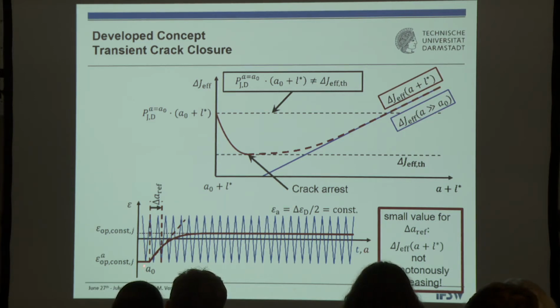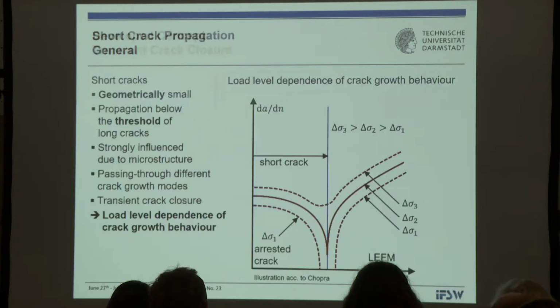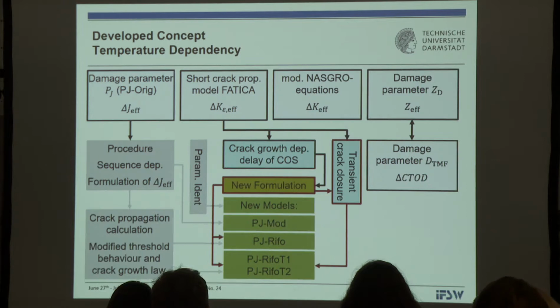So, and this can be done in the modeling by introducing a simple exponential equation here, and you can choose an appropriate reference length which steers how fast this approach is modeled here. So, and this leads us to the possibility that we can reproduce such well-known situations as shown here, that for example for short cracks you can find crack growth even below the long crack threshold, and the cracks come to an arrest, and sometimes if the amplitudes are higher you can pass this barrier. So this is now included in our modeling.